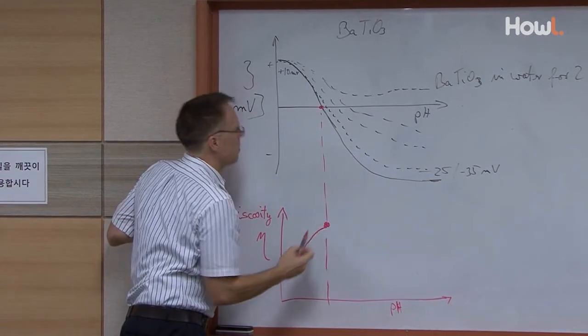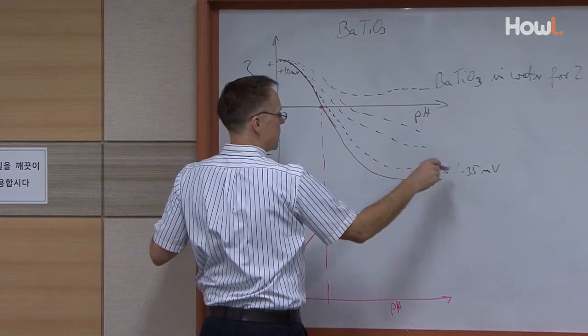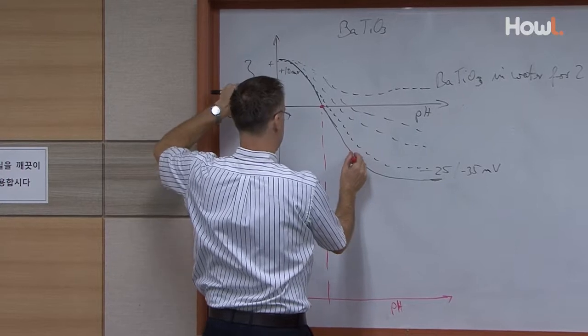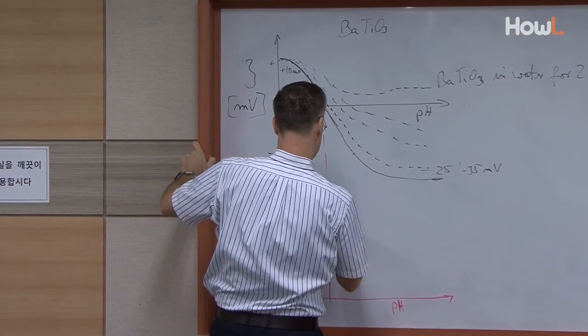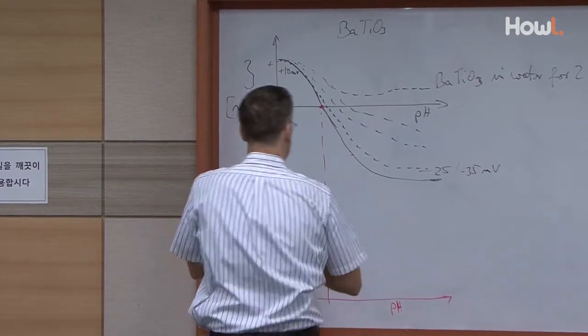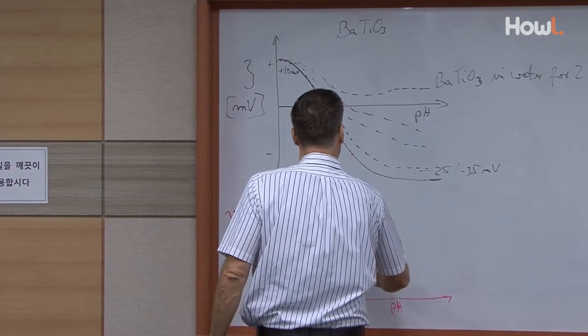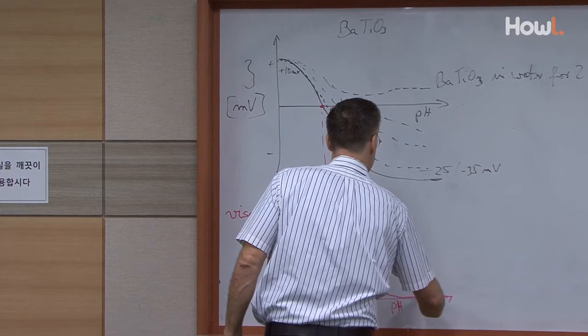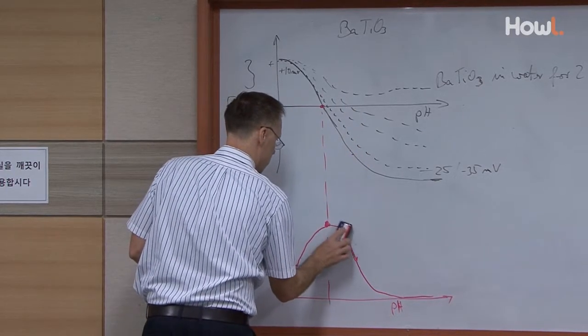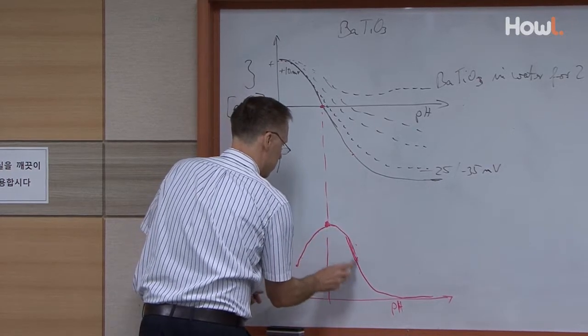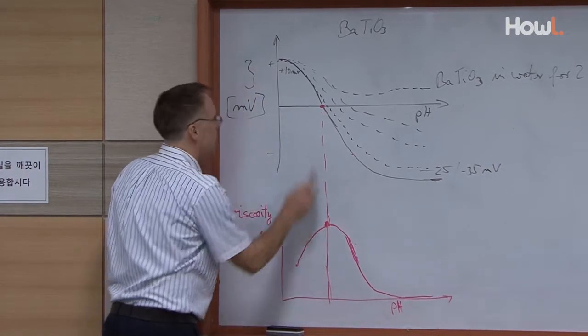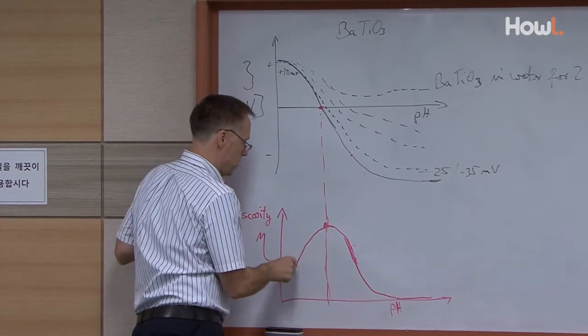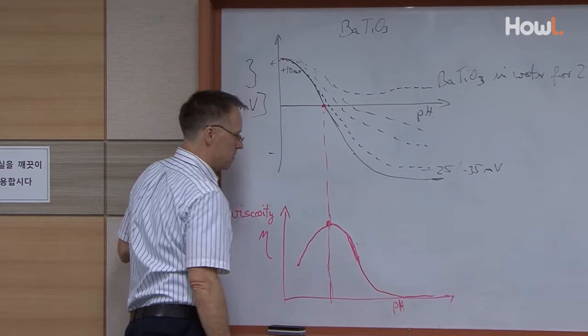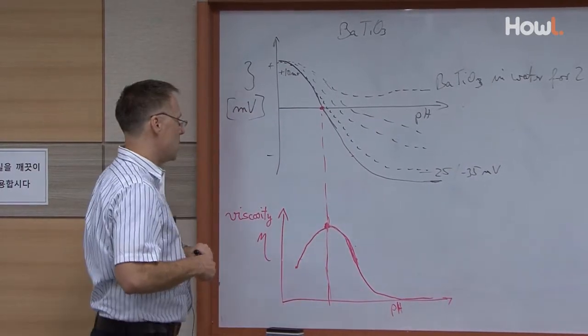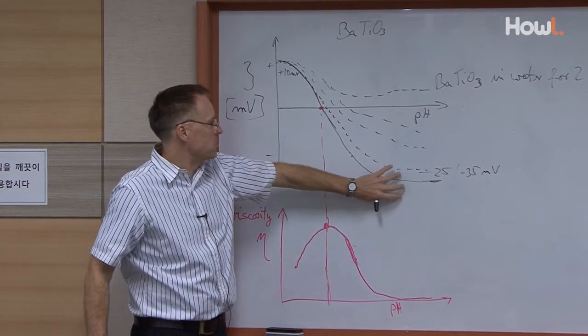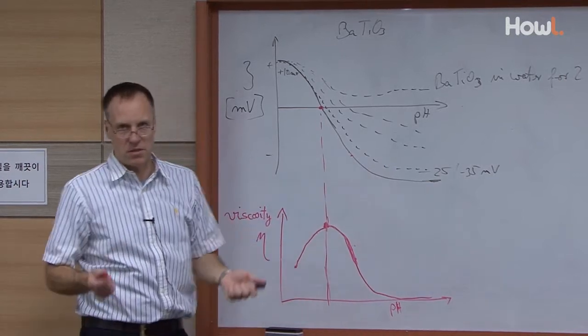so you expect that you get something like here. So this is one part of the viscosity curve. And now on this side, you see minus 25 or so millivolts, so about here is about the same as up here. So we need to draw it like this to here. And then from here, it goes down and levels out, of course. Yeah? So at this pH there is no repulsion, therefore sticking. Now you have some repulsion, here you have some repulsion. And the more repulsion there is, the lower the viscosity of the system. Yeah? And that's why for processing, if you can move it out to the higher potentials, then you get low viscosities. That's why we do this all the time.